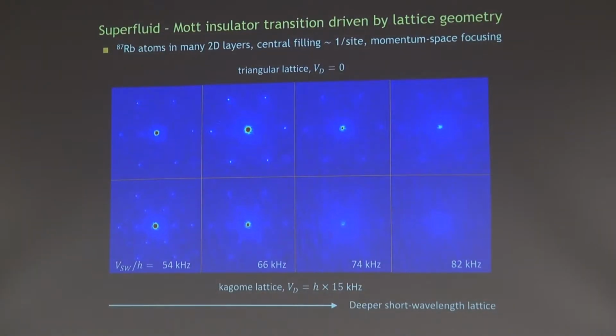So the standard analysis tool for whether the gas that you've trapped is in the superfluid or the non-superfluid phase is to examine the gas actually in momentum space, not in position space. And in momentum space, that's what these images are showing, if the gas has long-range coherence, then the momentum space distribution shows very sharp interference peaks, kind of like you can see when you're doing interferometry with coherent light beams. So that's, let's say, seen in these pictures. But when the gas is no longer long-range phase coherent and you don't have a superfluid, then these sharp peaks disappear and you get broader, mushy distributions in momentum space. So this is a standard panel of pictures that shows superfluids giving way to Mott insulating states as, in this case, the lattice is deepened.